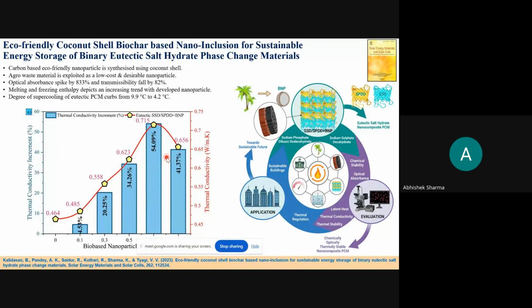We utilize those microparticles and nanoparticles in the eutectic phase change materials. And we found that we were able to improve the thermal conductivity by 54%, which is a very good percentage enhancement. When we talk about the bio-eco-friendly coconut shell, it is less energy intensive and converts waste into energy, for waste-to-energy applications. So that is what we were able to do.